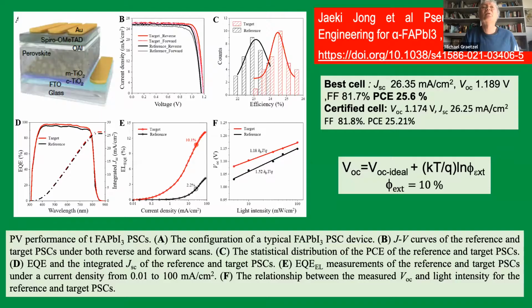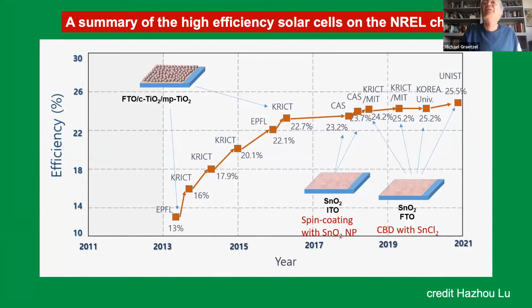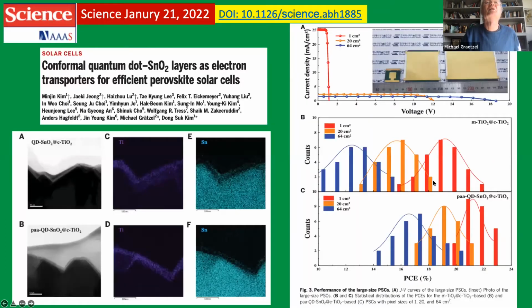The Nature paper is also on a passivator where we use formate to remove defects, but really very recently we have changed the electron selective contact, and we moved to tin oxide nanocrystals as electron selective contact. And that work was published this year in Science. And yeah, so let's take my sweater off. It's getting hot here in my office.